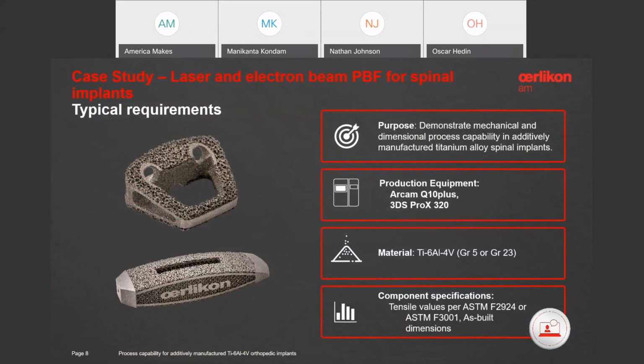The study covered two of the most commonly used titanium alloys in orthopedics, grade 5 and grade 23. The mechanical data was analyzed in accordance with ASTM F2924 and ASTM F3001 for tensile properties, and the dimensional data was collected by measuring the parts in the as-built condition.